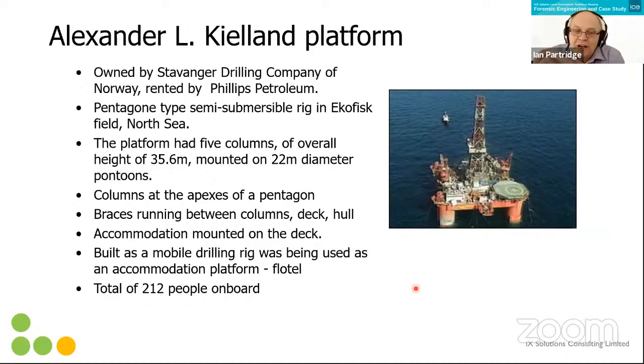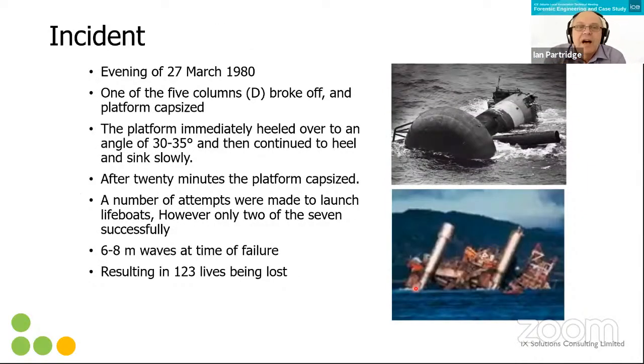It was a mobile drill rig, but it had been converted to an accommodation platform, a flotel as they call them in the industry. And at the time of failure, they had a total of 212 people on board. So on the 27th of March 1980, one of the 5 columns, D, as it was labelled, broke off and the platform capsized. So the minute it broke off, the platform heeled over to 30 to 35 degrees. It took a further 20 minutes for the platform to fully capsize to end up in this orientation.